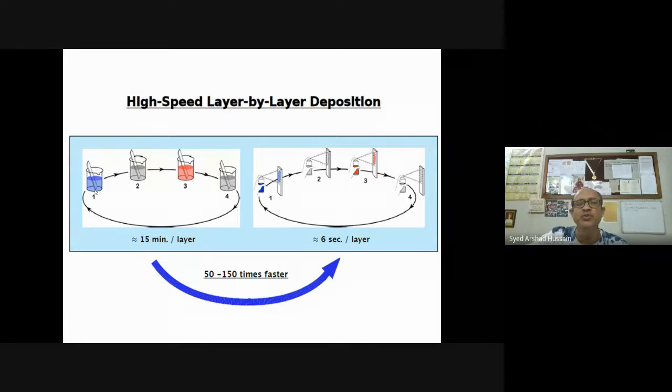If you go on increasing the deposition time, after some time there will be a particular time after which the absorption will not increase. That means all the positive charge of the substrate surface has been neutralized or interacted with the material you want to coat, so no further interaction is there. So you can have an idea about the time also. You have to play with this, but normally you need several minutes for this.